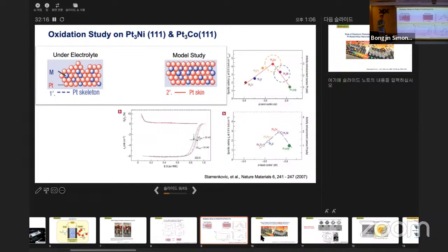But the thing that you essentially, as I understood, want to avoid is the transition metal getting to the surface. Yeah, well, this is 2007, so now it's almost 15 years. It turns out that platinum-3 nickel is still leaching out. It's very difficult to maintain that stability over many cycles. Platinum cobalt somehow works better than platinum-3 nickel, and they said it has a better cycle lifetime. And for the thing that I discussed here, everything about platinum cobalt forming the oxide, in actual electrolyte it may not work. It may all just leach out, and it may not be useful. It may not be really helpful.